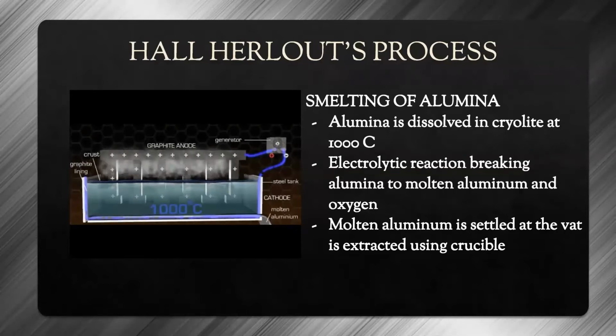In the Hall-Heroult process, the pure alumina is added to the molten cryolite and is dissolved at 1000 degrees Celsius, where they are mixed in pots or pot lines. These pot lines are rectangular cells lined with carbon blocks and insulation, which serve as the cathode. The anodes are attached to rods and suspended in the cells, which are used to conduct the electricity to the pots.